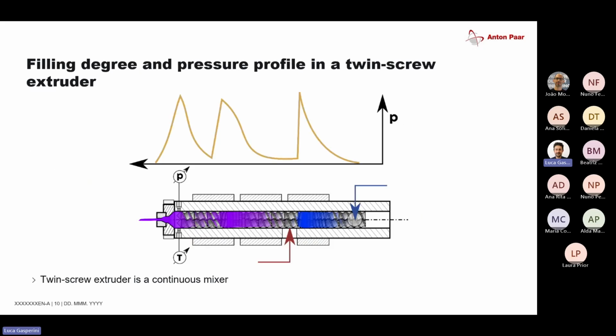Right here you see again the pressure profile of the same configuration which we examined earlier. So pressure rises here before we get into the kneading block. Then we get a maximum right here where the kneading blocks are, and after the backwards conveying elements, the pressure drops significantly. And then we have another mixing element, and then finally the die head, where the pressure rises again once the material is pushed out of the extruder. So, in a sense, the twin screw extruder is a continuous mixing process, and the screw configuration is a major part in the whole process development.